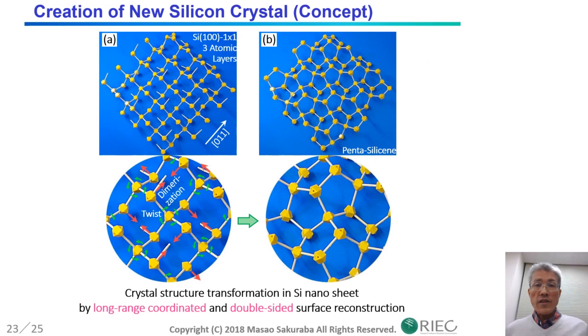These pictures show bird's-eye views for three atomic layer thick silicon 100 and the transformed pentasilicene by a ball and stick model. In my imagination, the transformation can be achieved naturally by long-range coordinated and double-sided reconstruction, in other words, dimer formation and twisting of mid-layer atoms. All dangling bonds, except for dimerization, are intentionally omitted in these models. Therefore, the dangling bonds should be terminated by some atoms, for example, oxygen atoms in a gate insulator in device applications.